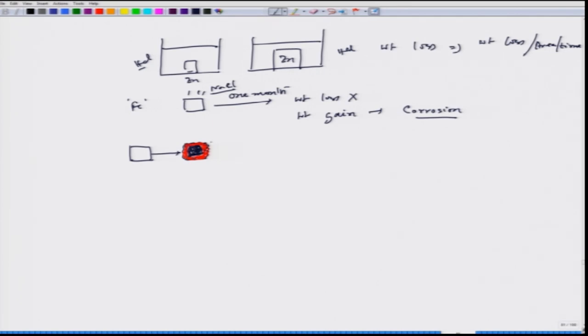Rest of the layer is nothing but oxides or hydroxides of iron. And since it is Fe2O3 or Fe(OH)3 or Fe(OH)2, now 1 mole of iron, if it forms oxide or hydroxide, the weight will be increasing if they are not getting detached from the surface. Now, how do you get the corrosion rate then?